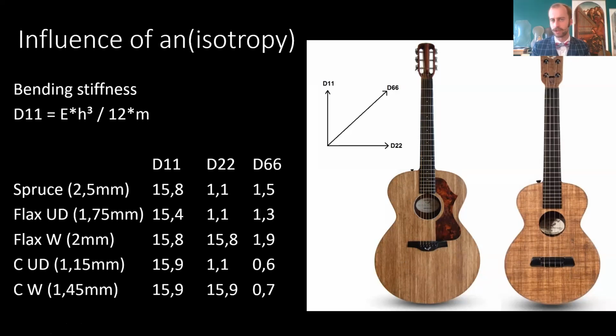So engineers use something called engineering constants. And actually they calculate this bending stiffness that we use as violin makers with some formula. So for example, here you have for the longitudinal direction a simplified formula, and E is the stiffness of the material in one direction. H is the thickness of the material. So you see it's to the third power. So the thickness has a very, very large influence on the stiffness of the plate, divided by 12, and then M. And M is a derivative of the Poisson ratio. So it's a different material property.